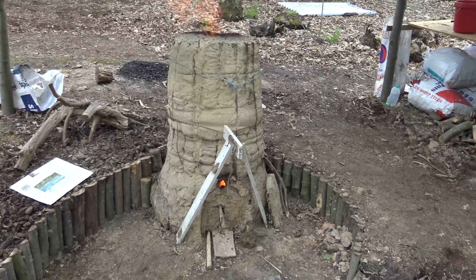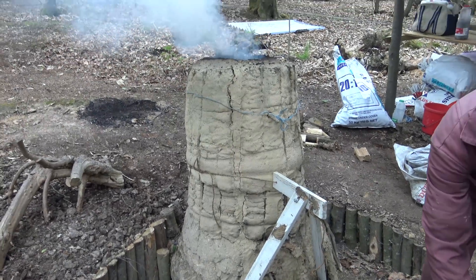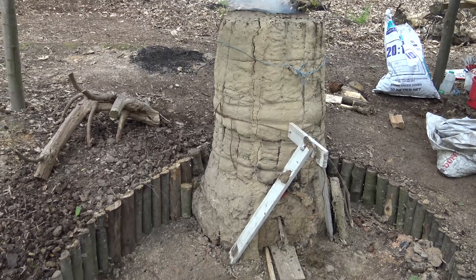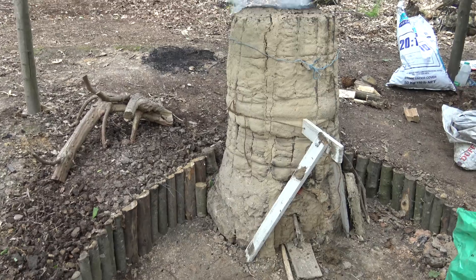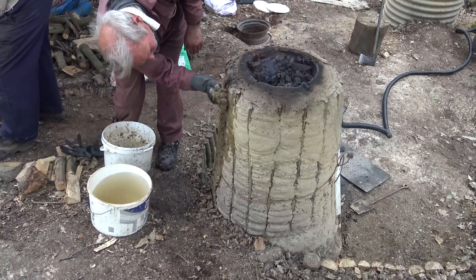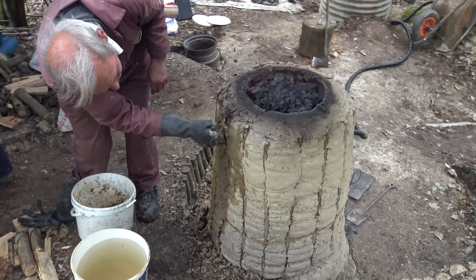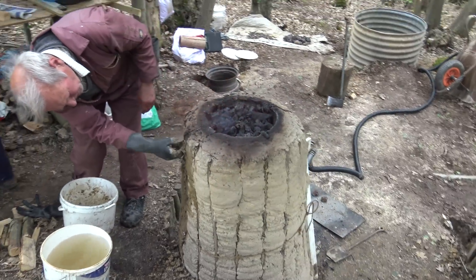What they created here, using clay from literally the tree roots at the side of this furnace — they built the furnace, and it had really thick walls. The idea basically would be to fill it up with charcoal to heat it up, and then as it got really hot, to about 1300 degrees C, to add the iron ore, which had been ground up and preheated to crack it and drive off some of the impurities.